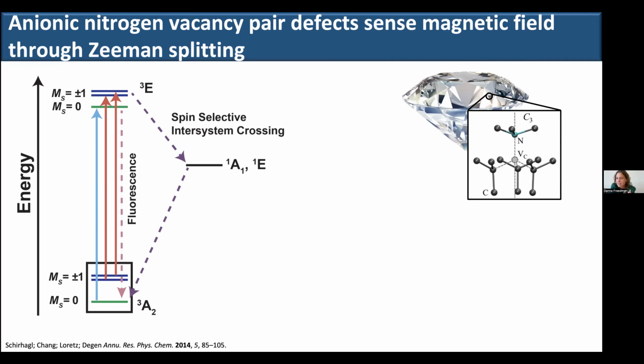And the reason that this is stable is because the bonds that you would have to break to move this defect are carbon-carbon bonds, and you wouldn't create a more stable location. So effectively, in more solid state terminology, the low mobility of the defect in diamond is the reason that it's stable. That's also the reason that you can't get this defect too close to the surface of diamond. In the other half of my lab, we work on this problem, but for solid state work, this is actually miraculous.